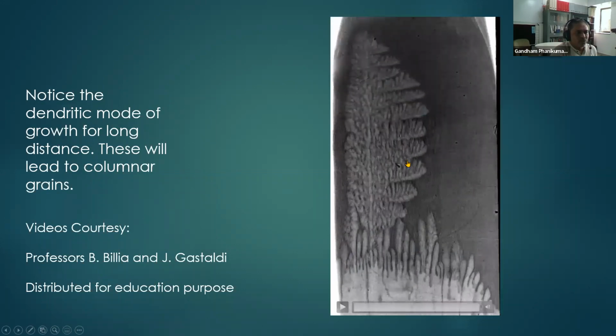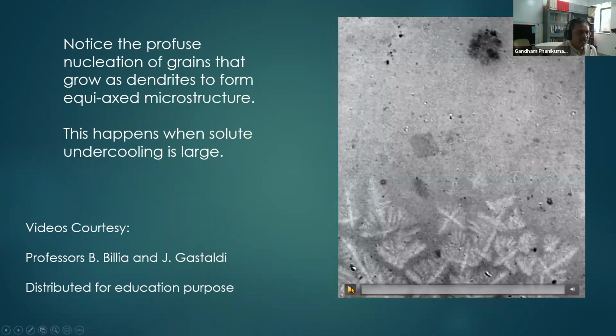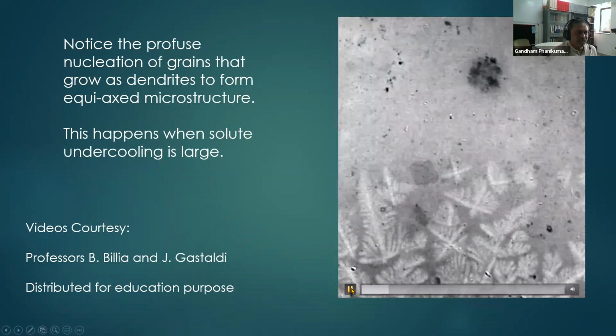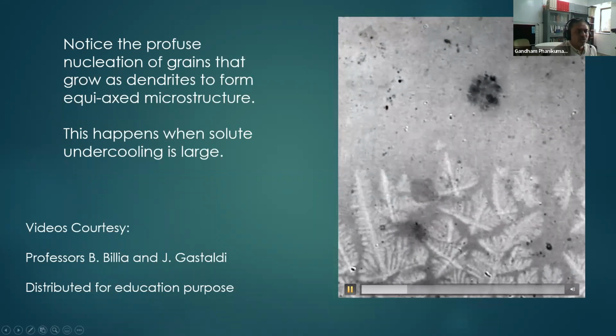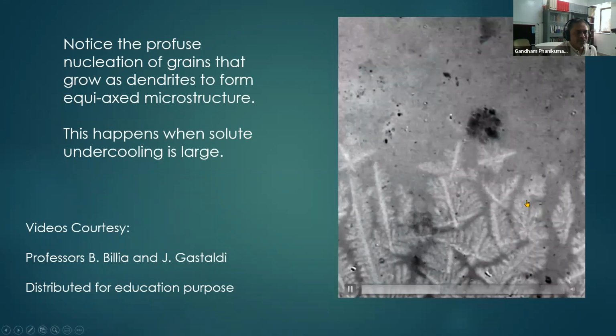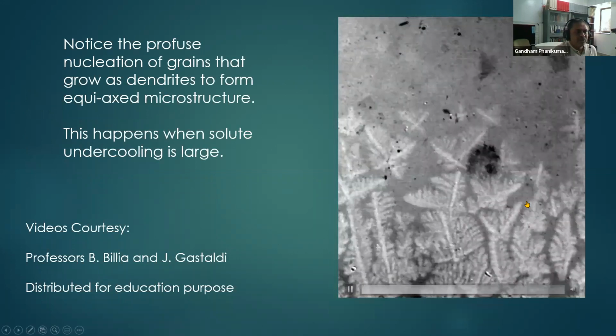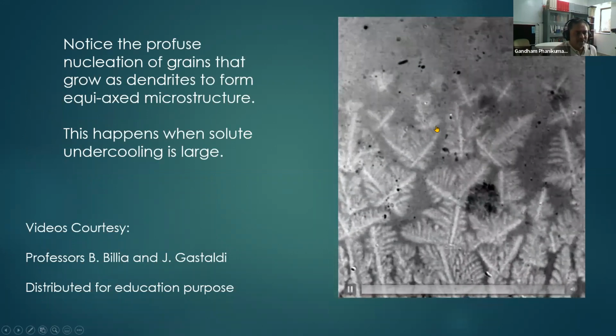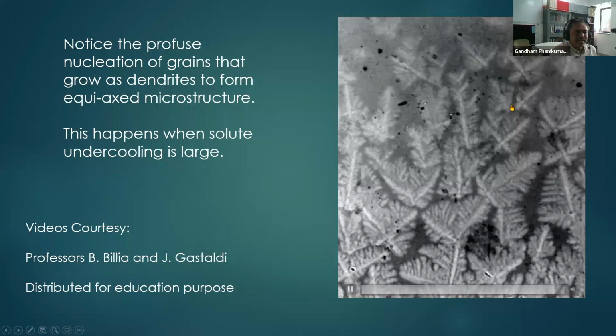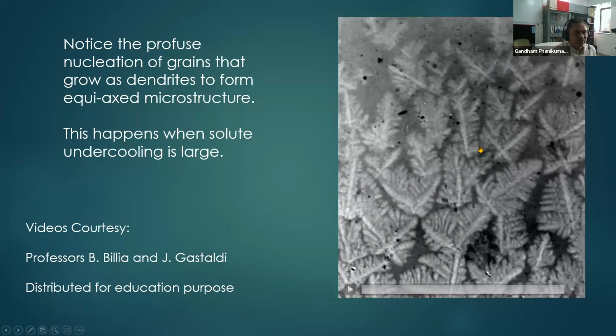And so we would like to be able to switch between these modes by the change of process conditions as we do. Here is a place where equiaxed growth is also recorded. Okay, so what I'm showing you is a synchrotron visualization of an aluminum alloy. So the so-called equiaxed microstructure formation is something that you are seeing with your eyes, except that it is enlarged and shown to you. But in the case of real additive manufacturing, it is all happening at a scale that is less than 1 millimeter for the entire zone that we are seeing.